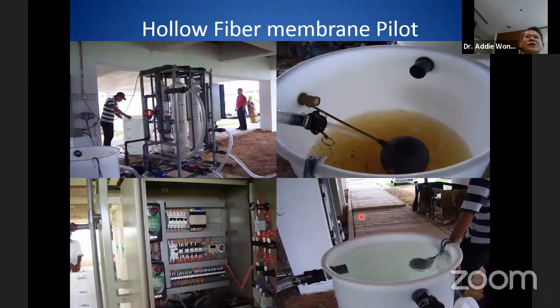This is a photo that shows the hollow fiber membrane. This is how it looks like. Inside there are a lot of hollow fibers, just like straws. You can see the raw water, which could be 70 to 80 NTU, pass through the membrane, and you can see immediately crystal clear water coming up, which is less than 0.5 NTU. This just shows the simple system in the box to control the membrane.